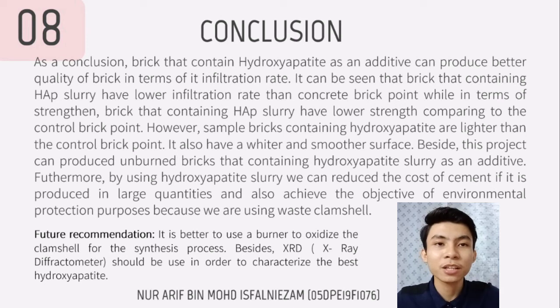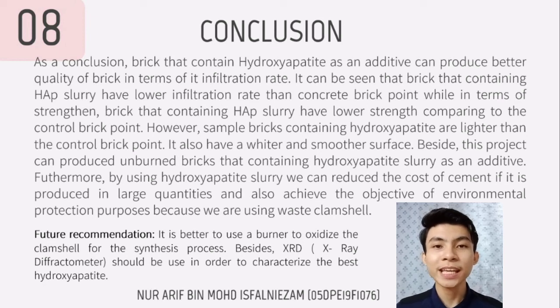Besides, this project can produce unburned brick containing hydroxyapatite slurry as an additive. Furthermore, by using hydroxyapatite slurry, we can reduce the cost of cement if it is produced in large quantity, and also achieve the objective of environmental protection because we are using waste clamshell. For the future recommendation, it is better to use a burner to oxidize the clamshell for the synthesis process. Besides, an XRD X-ray diffractometer should be used in order to characterize the best hydroxyapatite.